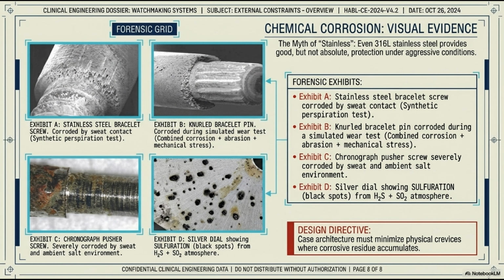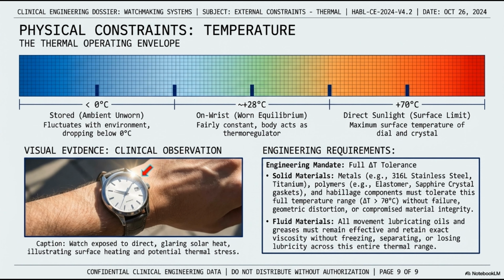Exhibit C is terrifying. This is a chronograph pusher screw, deeply pitted and rusted by a combination of human sweat and ambient coastal salt air. Exhibit D shows a different chemical reaction, sulfuration. This silver dial has erupted in black spots due to exposure to hydrogen sulfide and sulfur dioxide in standard urban atmosphere. The design directive is clear: you cannot rely on material chemistry alone. Your case architecture must actively minimize physical crevices where these highly corrosive residues can accumulate and fester. We move from chemistry to thermodynamics. Let's look at physical constraints, temperature.